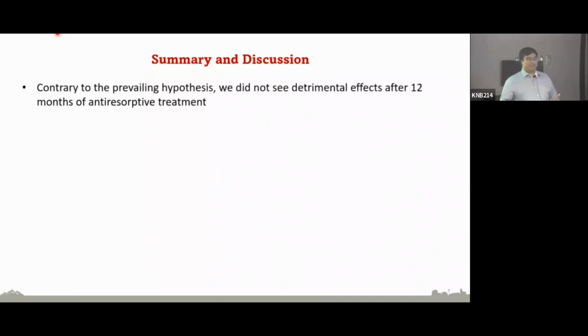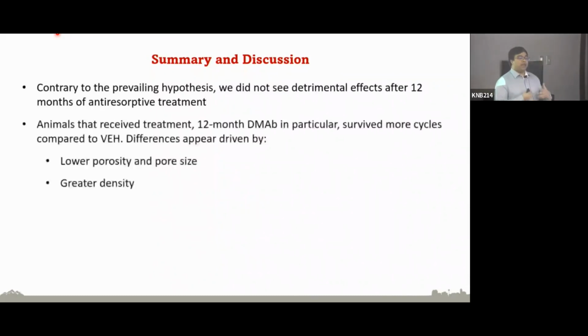So contrary to the prevailing hypothesis, we did not see any detrimental effects after 12 months of antiresorptive treatment. And in fact, we kind of saw the opposite. So we saw that antiresorptive treatment, and that 12-month denosumab group in particular, survived more cycles than the vehicle-treated animals. And those differences all seem to be really well explained by what the drug was doing to porosity, pore size, and density.